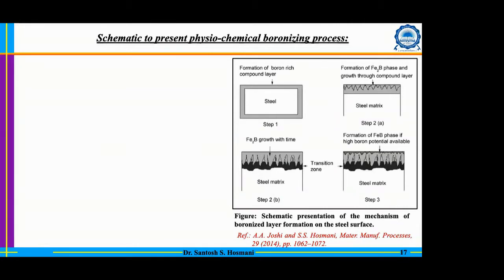Actually, what happens initially is there is a formation of a boron rich compound, and that compound is neither FeB nor Fe2B. It is just a boron rich compound, and then there is a nucleation of Fe2B, and then it will grow as a sawtooth morphology. Again, that morphology depends on the composition of the steel. If you have the low alloy steel or the medium alloy steel, most of the time people have observed a sawtooth morphology of these borides. However, as you keep on increasing the concentration of alloying element, your morphology will change. It will become a smoother morphology than the sawtooth morphology. That I will discuss later, because that is also an interesting aspect we need to understand.